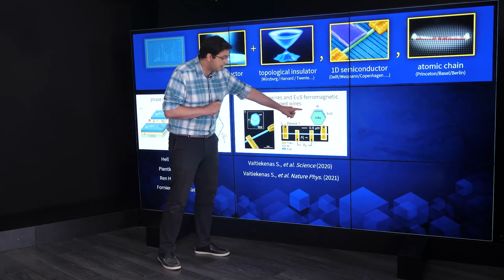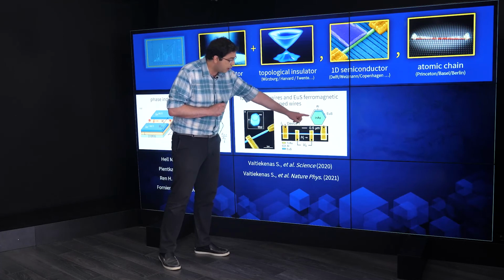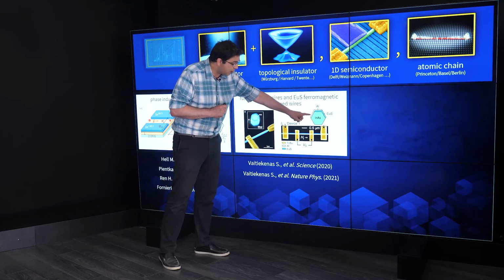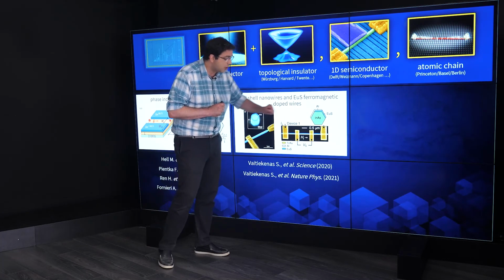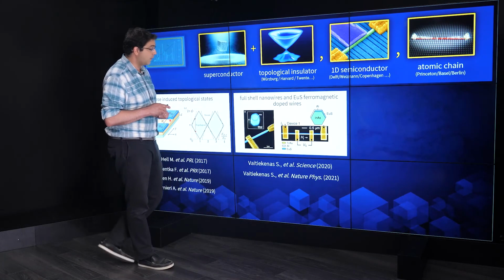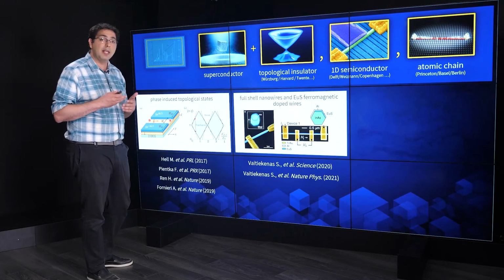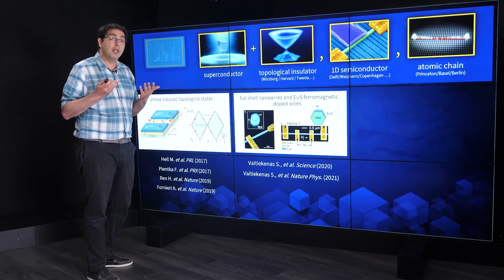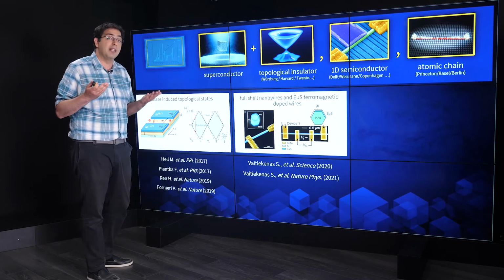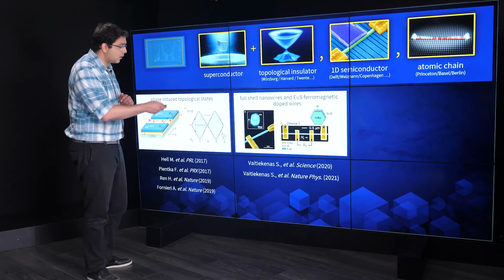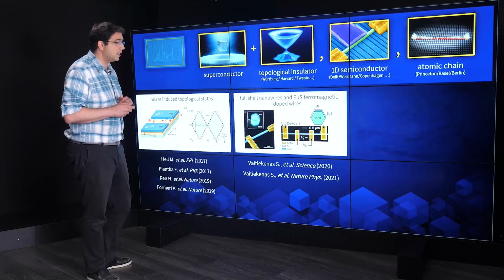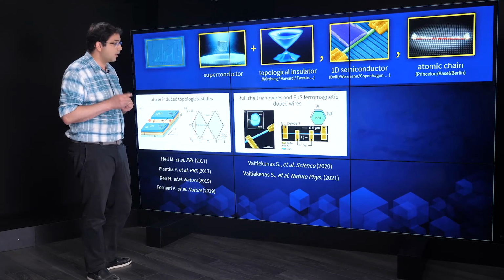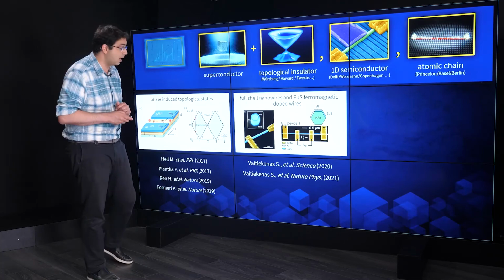This is very interesting. It's a tri-layer junction. So you have indium arsenide, which is epitaxially grown with aluminum, but also epitaxially grown with europium sulfide. And then you basically eliminate the need for an exterior magnetic field. So also here they were able to show zero bias peak signatures which are associated with Majorana zero modes.